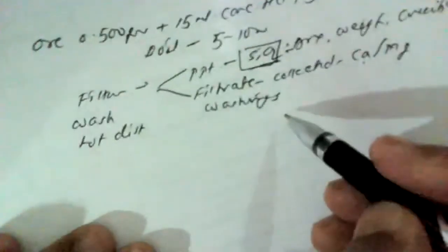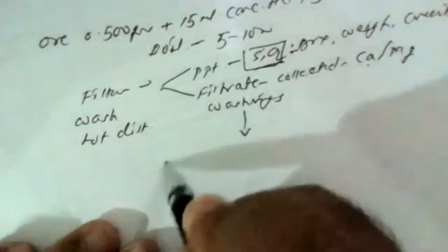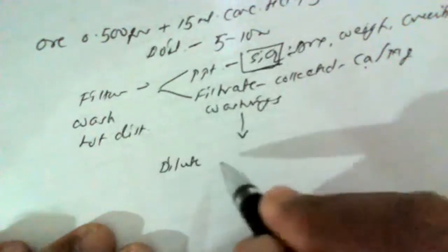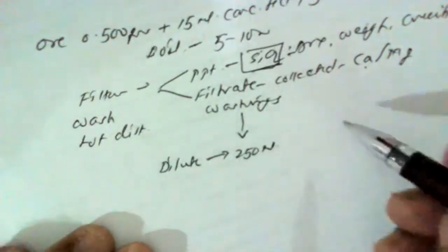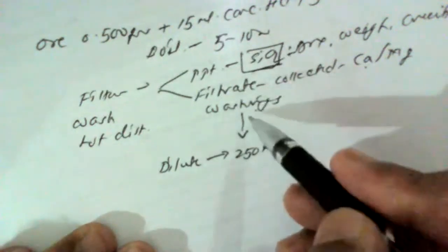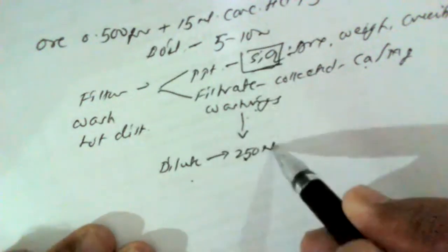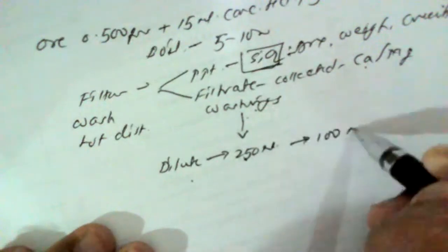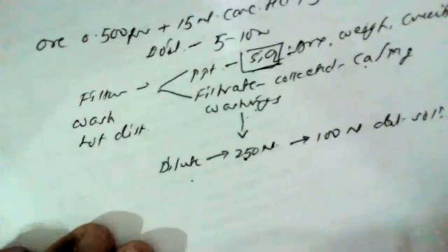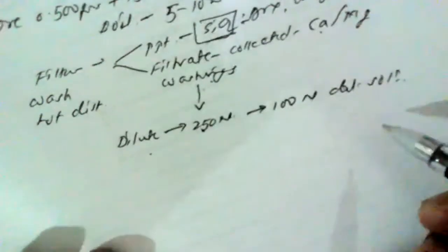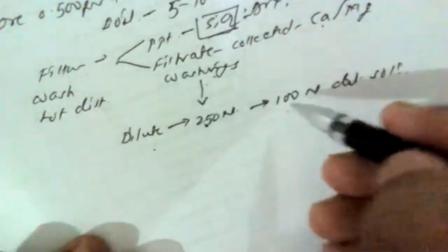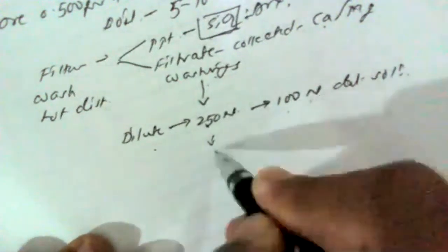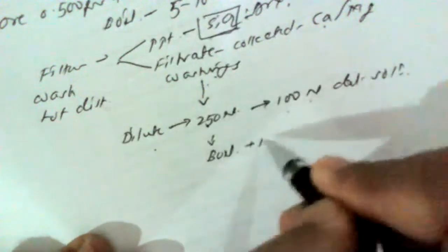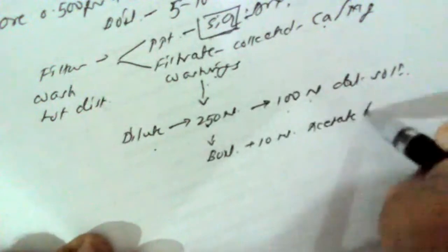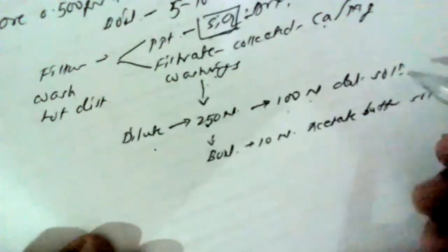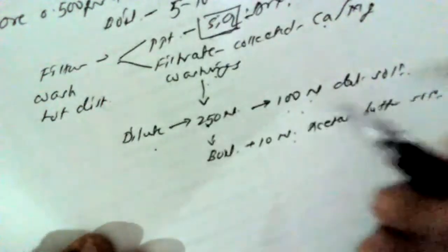Now to determine the calcium and magnesium content from dolomite ore, first of all, we have to dilute the filtrate and washings to about 250 ml by using distilled water. From this solution, we take 100 ml of the diluted solution for our estimation of calcium and magnesium. This 100 ml solution we have to boil carefully. Then we add 10 ml of acetate buffer solution, which is already prepared. Ready-made solution is there. We just have to add 10 ml to this 100 ml solution after boiling.